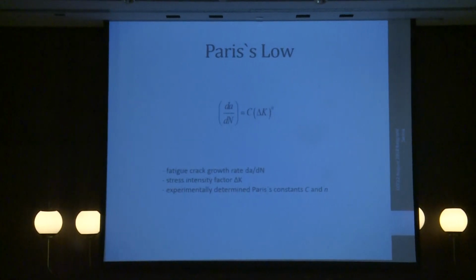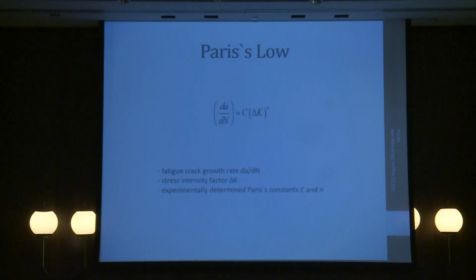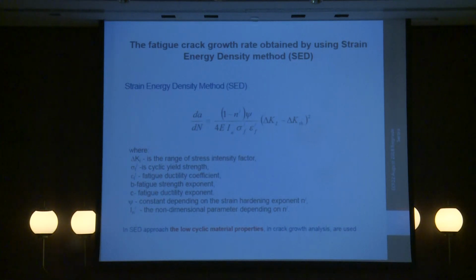Here on this slide is the equation for the Paris law. This is the conventional law for analysis of fatigue crack growth. Here we use the dynamic characteristics of materials, that is C and n, the Paris constants. We determine them using experimental methods, and then we know the fatigue crack growth rate. Maybe a little bit better method is the strain energy density method, because this method uses the low cycle characteristics of materials. We get those characteristics from experimental testing for the crack initiation, and the same characteristics for the crack growth. So we can determine those characteristics one time.